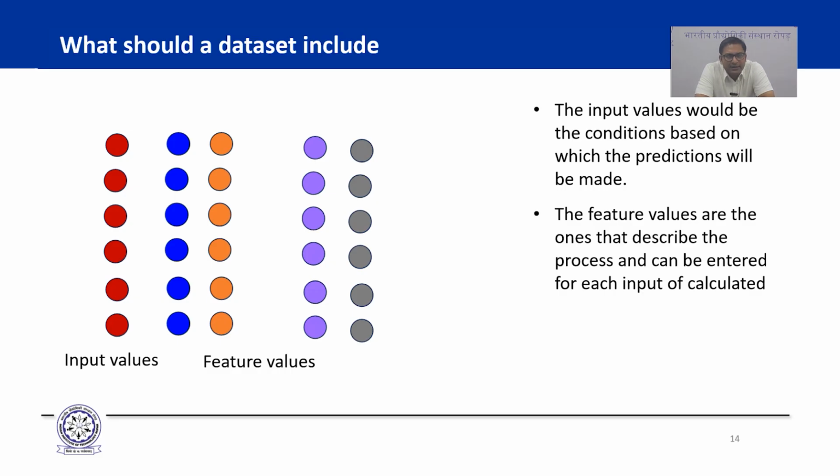Usually that has a challenge, because that would mean if you want to go with any arbitrary input, you need a huge repository of these features. So a lot of these features are actually things that you can calculate. For instance, suppose you want to predict the phase stability of different materials. We know that because of the Hume-Rothery type of rules, the valence electron concentration becomes an important parameter. The valence electron concentration is something that you can compute based on the composition of the material. And therefore, if your input is the composition of the material, the valence electron concentration is a feature that gets automatically calculated when you featurize your dataset.